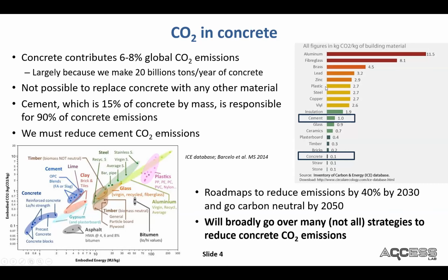In terms of building materials, the only materials with lower emissions than concrete on a mass basis are probably straw and stone. Cement has about 10 times the emissions of concrete, and this is interesting because it's only 15% of concrete by mass, but it's responsible for about 90% of concrete emissions. There are curves like this in the literature.